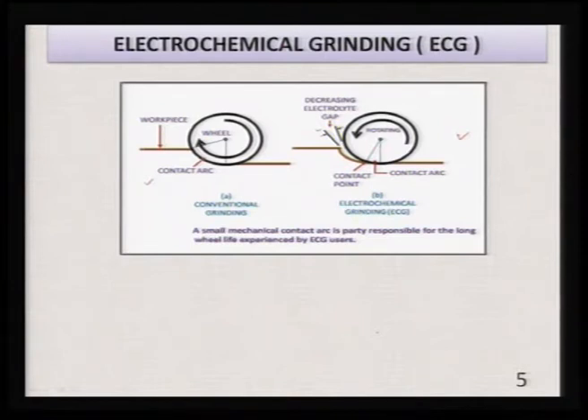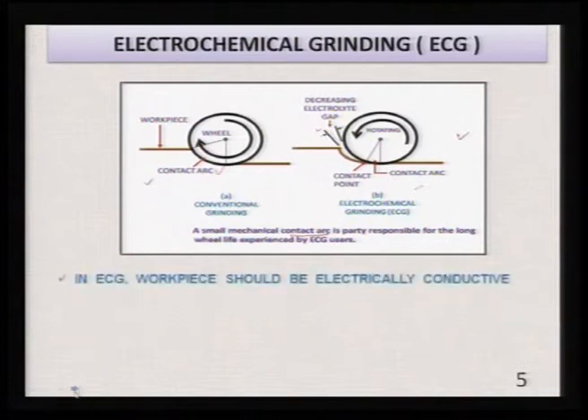A small mechanical contact arc is partly responsible for the long wheel life experienced by electrochemical grinding users. That means in electrochemical grinding the life of the grinding wheel is much larger than in the case of conventional grinding. You can see here that the contact arc is much larger in case of conventional grinding as compared to electrochemical grinding. That is why the grinding wheel life is much larger in case of electrochemical grinding compared to conventional grinding.